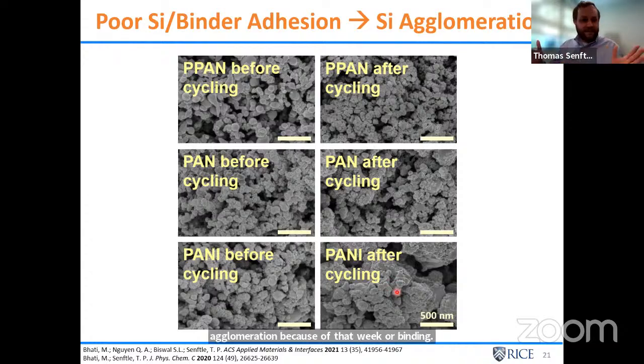And this happens as a bulk interfacial phenomenon, right? If we looked at just the chemistry of how one chain binds onto the surface, we would have missed this. So you really have to be able to scale up beyond just a simple picture of looking at what specific bonds are forming. You need to understand the collective behavior at the interface.